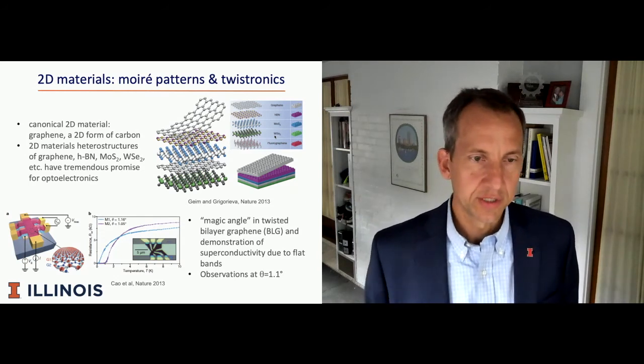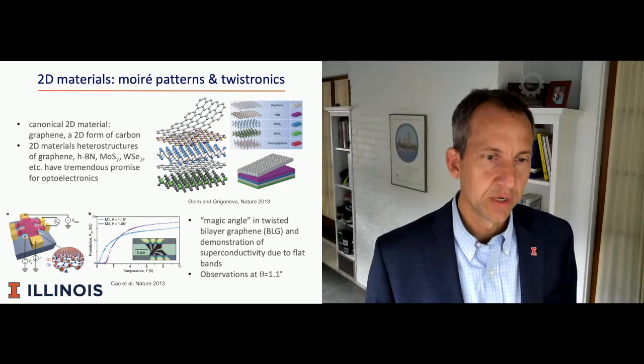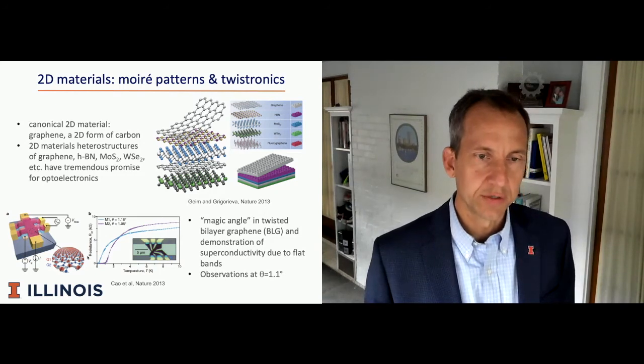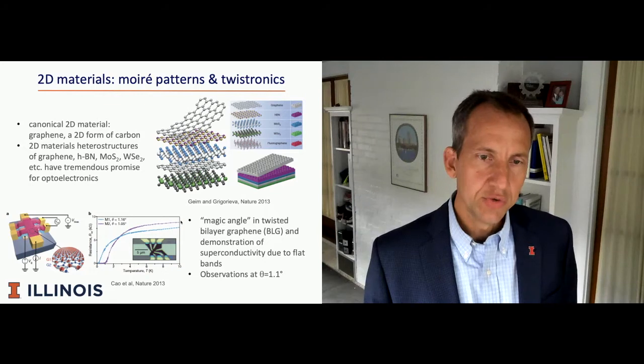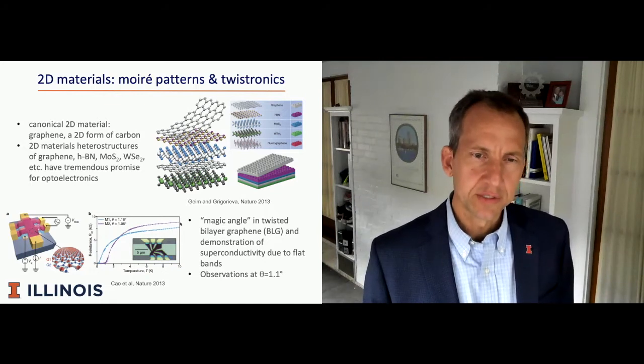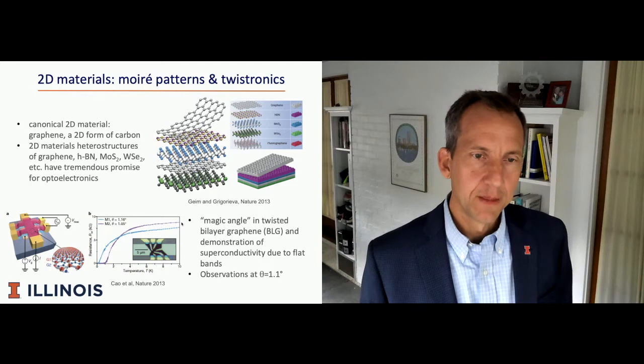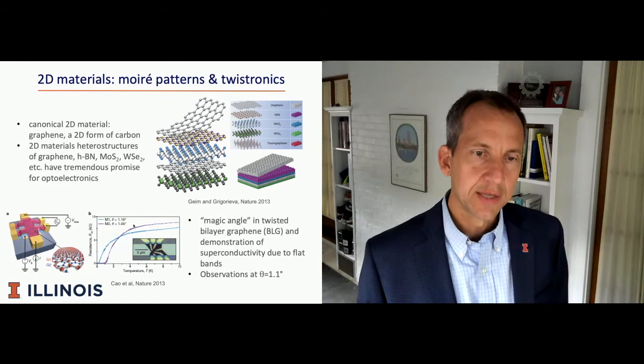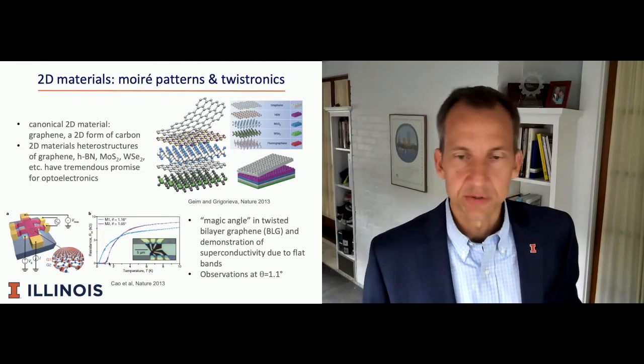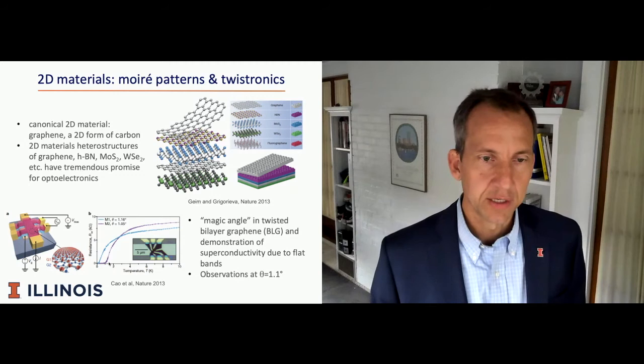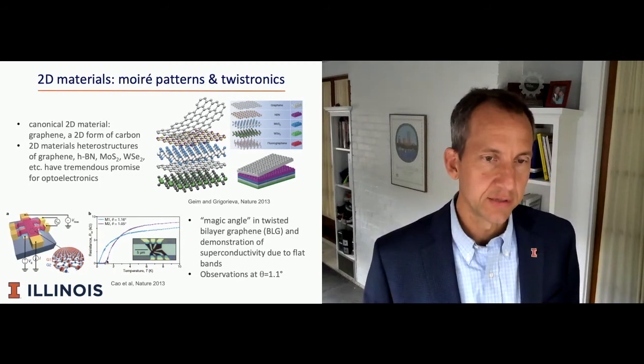superconductivity. And so what's shown in the image is the arrangement of G1 and G2 layers on top of one another. And at 2 different twist angles that are very close together, one is 1.16, the other is 1.05, one finds that in the case of the 1.05 degree twist angle, as temperature is reduced, as we go lower and lower in temperature, while still at a finite temperature, the resistance goes to 0. So this is the observation of superconductivity. And you can see that this feature is very, very sensitive to twist angle.